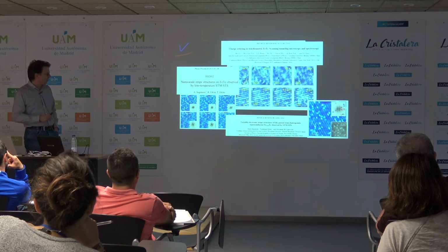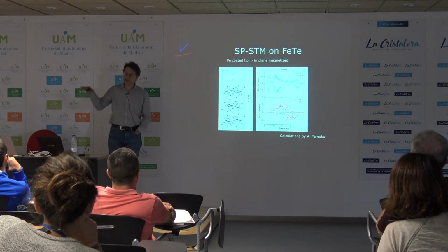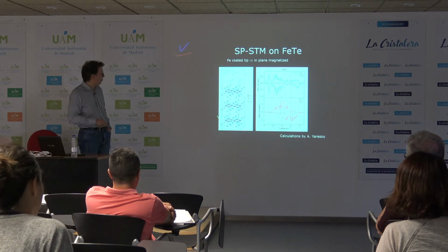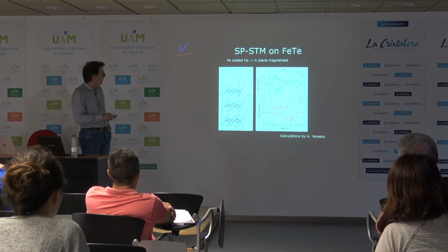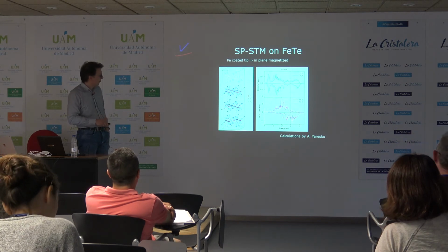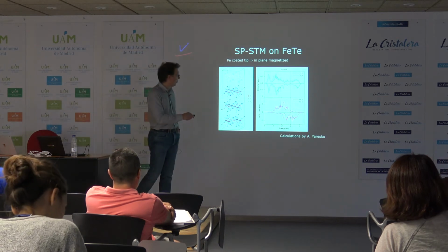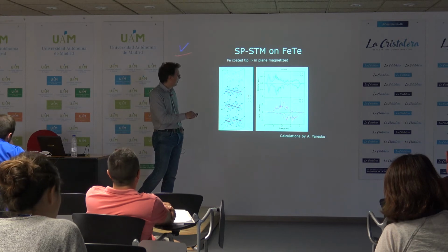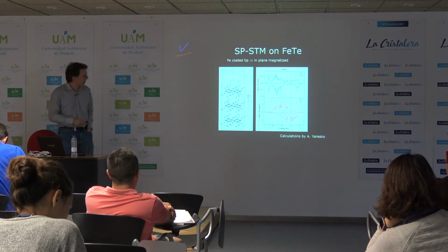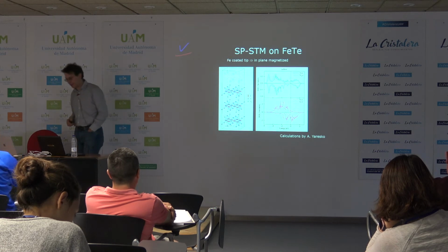One of the questions we were wondering is why we see magnetic contrast in the material, given that the top layer is tellurium, which is a non-magnetic element. So we asked Sasha Yaresko to do DFT slab calculations of the surface. And what one finds is that at the surface, the iron surely is spin polarized, that's to be expected. But also on the tellurium atoms at the surface, at the Fermi energy, you have a substantial difference between spin up and spin down density of states. So the tellurium states are also reasonably strongly spin polarized.